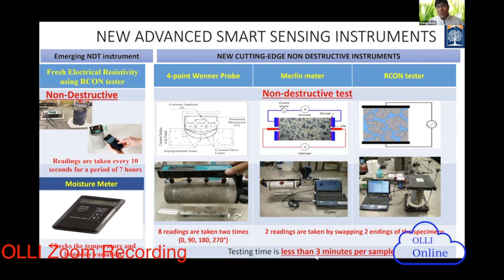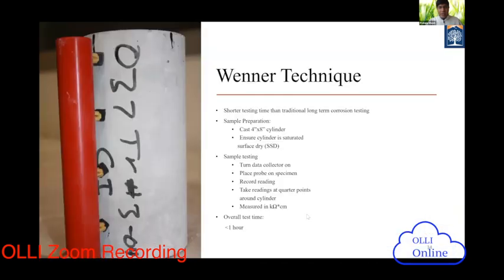You can imagine when you do the destructive testing and big corrosion testing, you have to measure the concentration of the chlorides in the cathode and the anode sample, which I can show you. This is the Wenner probe technique. This is so easy, just touching 4 probes on the sample, 4x8 cylinder, turn the detector on, place these 4 probes, 1, 2, 3, 4, and take the readings at quarter points, because concrete has quarter points, 90 degree, 180, 270, 360. So then you get your resistivity in kilo ohm centimeter.